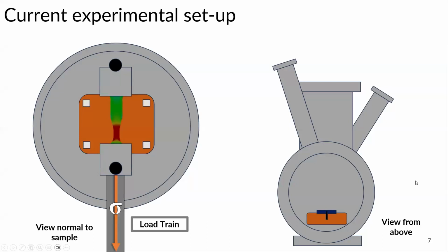So this is my current experimental setup. I conduct all of my experiments in the Michigan Ion Beam Laboratory. On the left, you'll see a view normal to your sample, and then on the right, you'll see a view from above. And so I attach my sample to a load train through friction grips. So I place my thin foil between two friction clamps, load it in vertically, and then I attach a load train in which we have a constant load applied to our sample. It is backed up against a copper block.